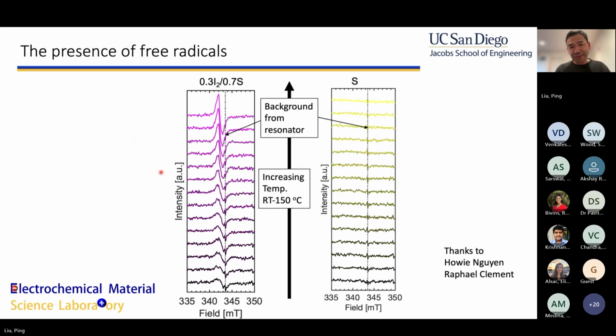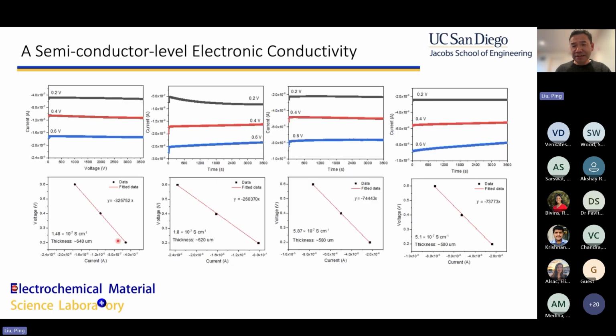So we did a lot of characterization work on the material. We used electron paramagnetic resonance spectroscopy to catch the free radicals. It turned out when we make the material, it is very rich in free radicals, unlike elemental sulfur. And what does that mean? We measured electronic conductivity, and the material behaves like a semiconductor rather than a perfect insulator. So this is wonderful, even though 10 to the minus 7 does not sound very exciting.